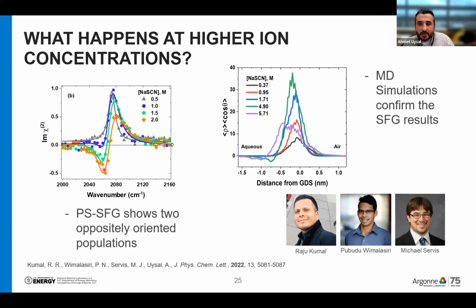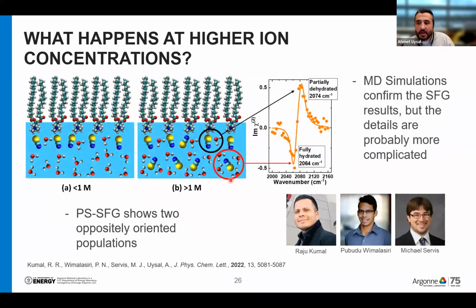And very interestingly, the peak position for these down-looking thiocyanate ions is different from the up-looking ones. It suggests that the coordination environment is different for up-looking and down-looking thiocyanate molecules. And Michael and Pubudu did some MD simulations confirming the overall picture here, but it is a little bit more complicated than what we can understand from the SFG experiments alone. So our studies are going on with this, and we're hoping to get a better understanding of the system with the help of MD simulations.